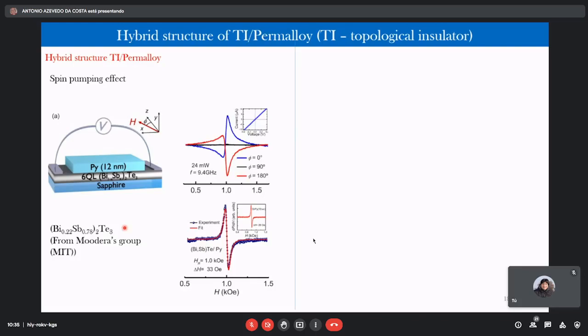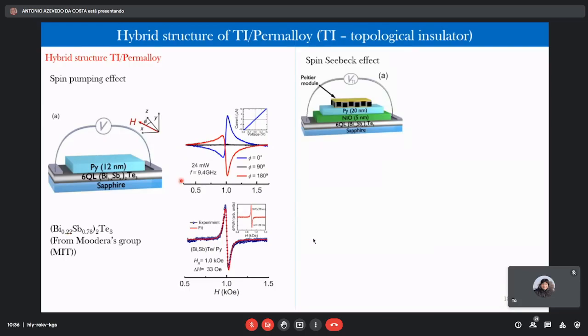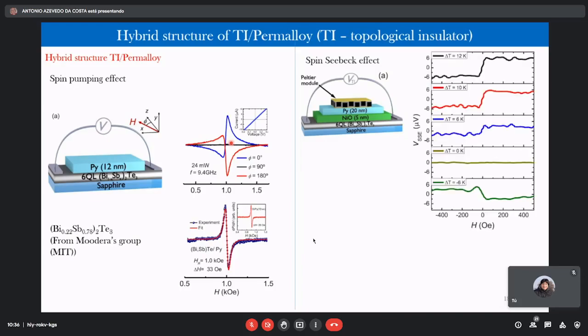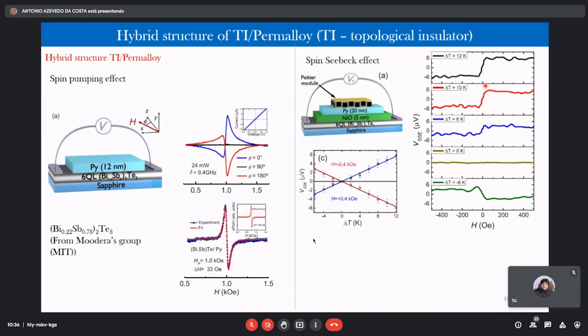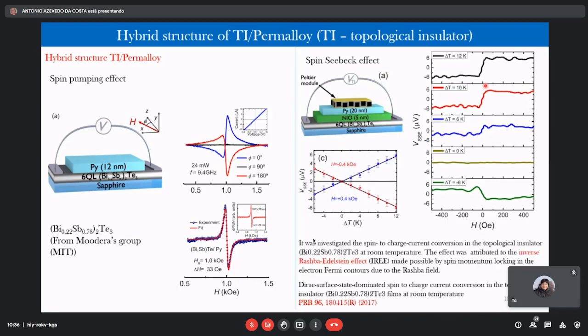and we measured the ferromagnetic resonance of permalloy. It has an asymmetric component which is due to magneto-galvanic effects and so on, but this is clearly a signal which comes from the conversion of the spin to charge current. And we also measured the spin-Seebeck effect, in which we had to insulate the permalloy from the topological insulator by a nickel oxide layer to avoid the anomalous Nernst effect. And we measured a very weak signal due to the spin to charge conversion by this thermal spin pumping effect. So all the characteristics are there. We published this many years ago.